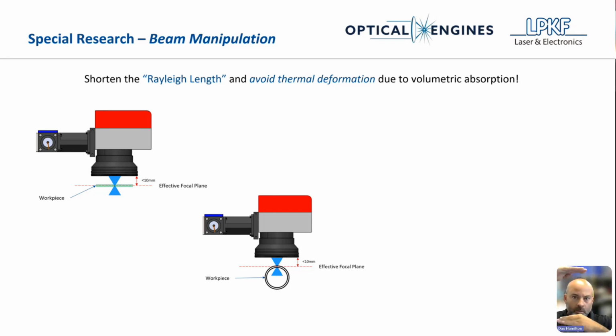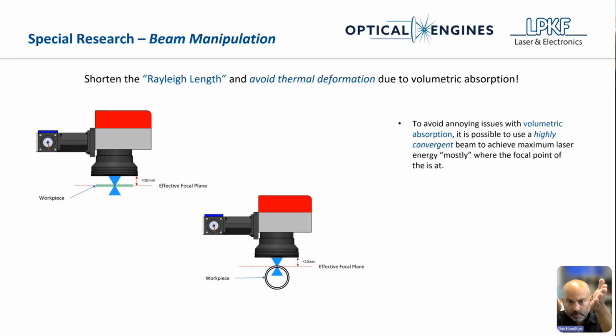And by bringing that scan head or the F theta lens, basically the whole assembly, down to the point where we're using a highly convergent beam. Okay, so we're taking typically a beam that's probably 10, 15, 20 millimeters diameter. In some cases, may not be exactly that with the 1940 nanometer. And we're converging that down onto the workpiece so that effectively only the focal plane where we actually want to weld is in true focus within what's called the Rayleigh length. So we're shortening that Rayleigh length down to the point where we're doing all of the effective work inside the weld joint.